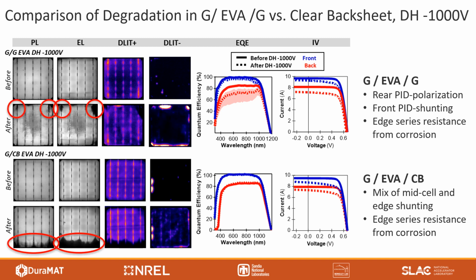Using the images, we can see some shunting in the DLIT minus image for the after stress scenario. There's lots of shunting around the cell perimeter for the glass-glass sample, and some more shunting in the cell interior for the glass-clear backsheet case. In addition to shunting, we also see series resistance effects, which is most obvious by comparing the PL and EL images. For the glass-glass sample, you see it in the upper corners, and for the glass-clear backsheet sample, you can see it along the bottom edge.